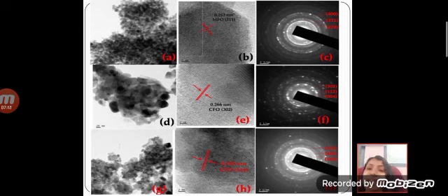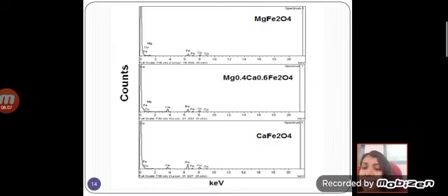Figure C shows the lattice planes calculated, that is 440, 400, 311 and 220 planes, corresponding to that of the cubic spinel structure, while the planes detected from the SAD pattern of calcium ferrite show an orthorhombic structure. This is the EDX pattern of the samples. We can see MgFe2O4, and you can see that calcium starts appearing in the sample when calcium is added, and we can see the EDX spectra of calcium ferrite.